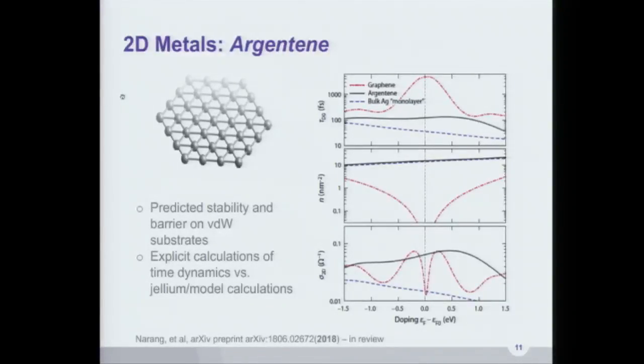Right? So now the challenge with Argentene, unlike graphene, is it doesn't have a nice, happy partner like hBN that interacts just enough that it takes away from the soft phonon modes, but not so much that it messes up the electronic properties. Right? I told you it changes the electron-phonon times, but not the electron-electron times. Well, in the case of Argentene, we're looking for that magic substrate that has the same kind of thing where it doesn't take away from the electronic properties of the freestanding layer. Everything we've predicted for this has been for the freestanding case.